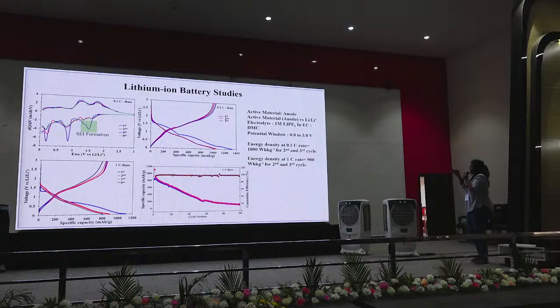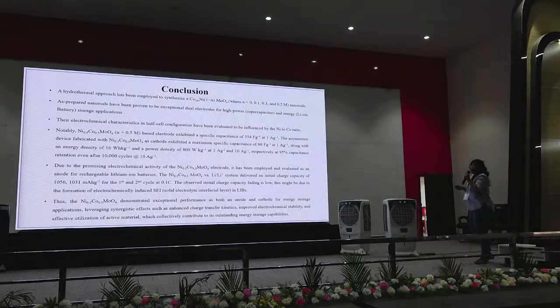The energy density I've got is around 1000 watt hour per kg for the second and third cycles at 0.1 C rate, and for 1 C rate I've got 900 watt hour per kilogram. So this is all about the lithium ion storage.